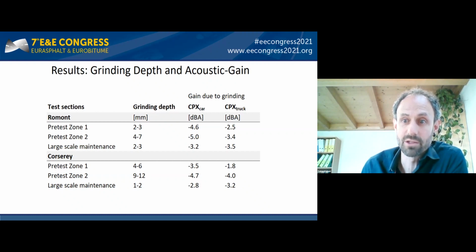In this table, we can compare the values from the pre-test zones and the large-scale test sections for each road, Romont on top and Corserey at the bottom. In the pre-test, we also varied the grinding depth, which we did by multiple grinding passages of the machine. In Romont, the highest depth was 4 to 7 millimeters, and in Corserey, we achieved 9 to 12 millimeters.